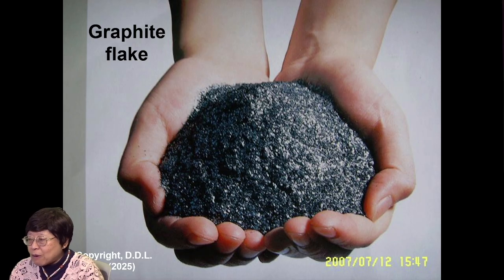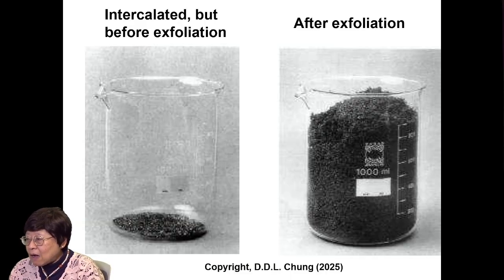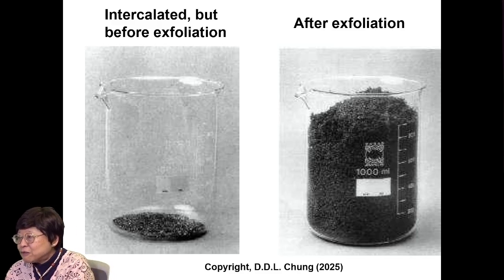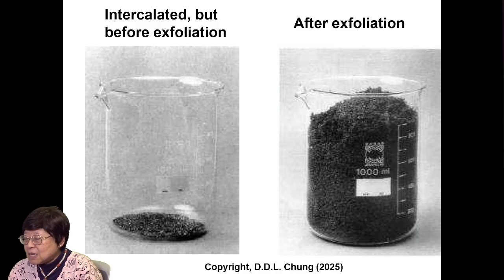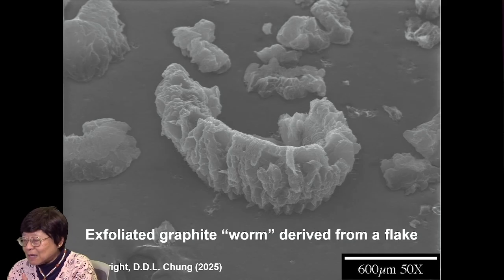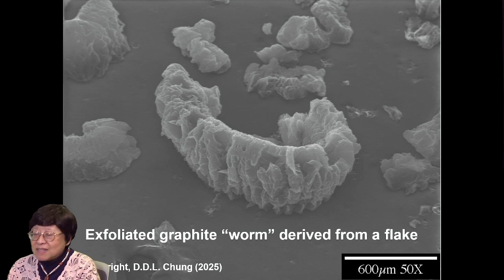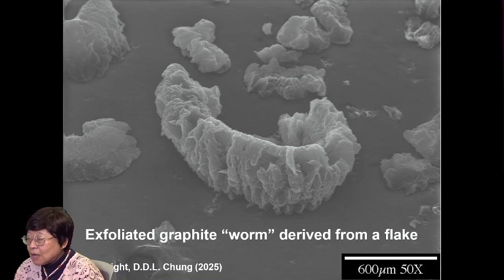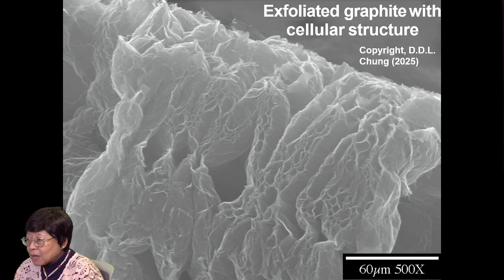Flexible graphite is made from graphite flake. The flakes are intercalated. On the left is after intercalation, and then on the right is after the exfoliation of the intercalated flakes. And the exfoliation causes huge amount of expansion, resulting in something looking like a worm and having this accordion kind of structure, cellular structure. This is actually called a worm, which is derived from a flake after tremendous expansion along the axis of the flake, vertical axis. And this is that exfoliated graphite with the cellular structure.